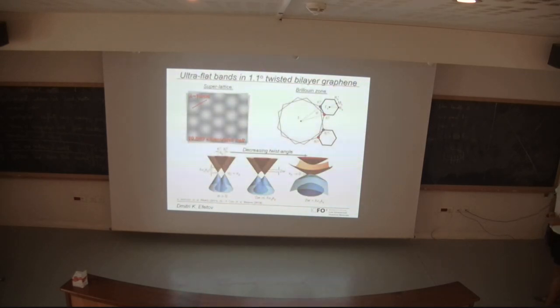Okay, and for a very specific angle of 1.1 degrees, what happens is that we end up in a situation where we have a lattice constant of the Moiré potential of 14 nanometers. So 14 nanometers is something like 50 times bigger than the lattice constant of the carbon lattice itself. And if one would count up the carbon atoms which are in one Moiré lattice unit cell, you would find that these are in the order of 10,000 atoms per unit cell.